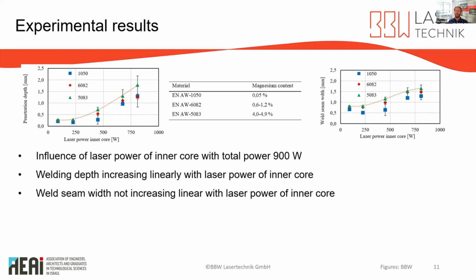The penetration depth increases linearly with laser power of the inner core. And in contrast to the penetration depth, the weld seam width is not increasing linearly, what you can see here on the right side. The graph flattens at a higher laser power, indicating that for higher laser power of the inner core, only penetration depth increases, but weld seam width reaches a saturation.